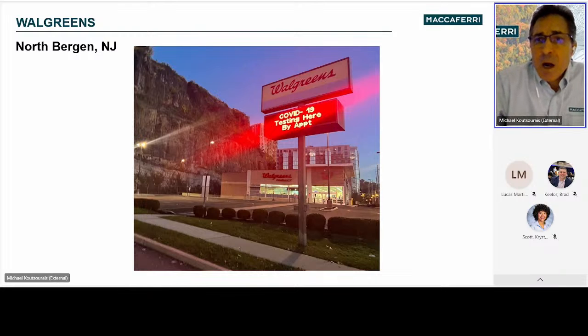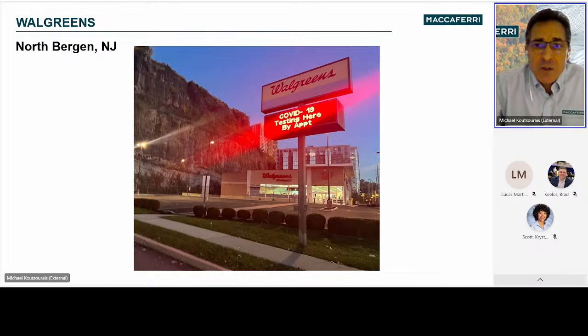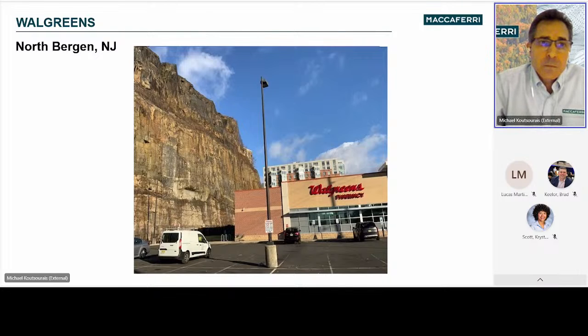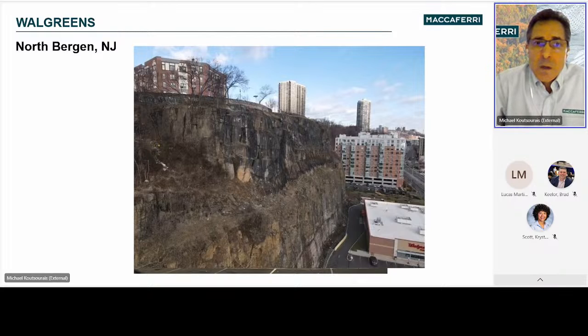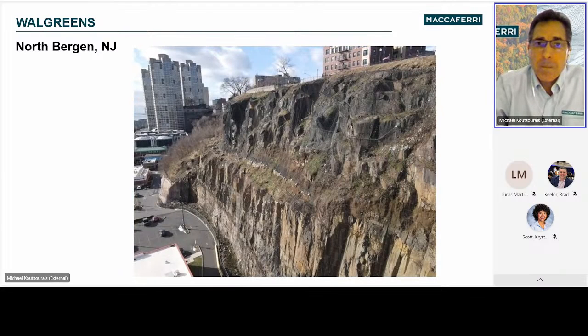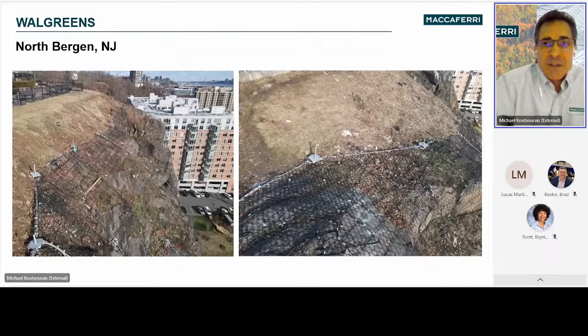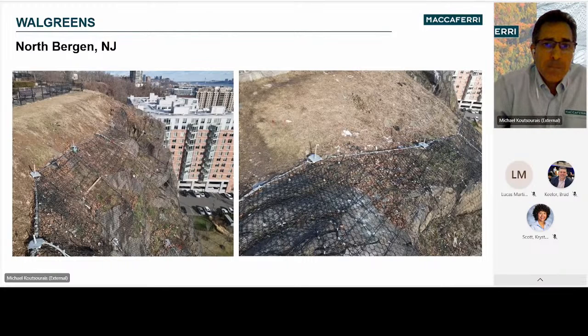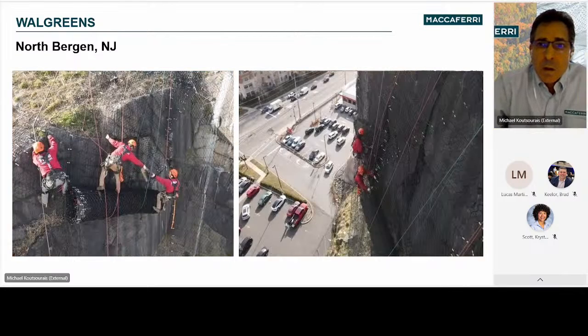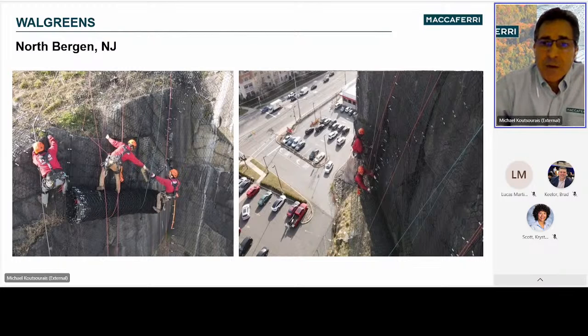Here is a 210 foot high pin drapery necessary for the construction of this Walgreens in North Bergen, New Jersey. Approximately 54,000 square feet of RockMesh 3030 PVC coated black was installed by Philco Industries. About 110 number 8 bar anchors were installed on a 10-foot spacing along the perimeter, 6 to 8 foot into rock. And number 11 bar anchors were installed as needed throughout the interior of the rock face.